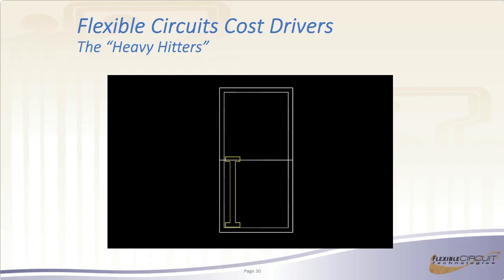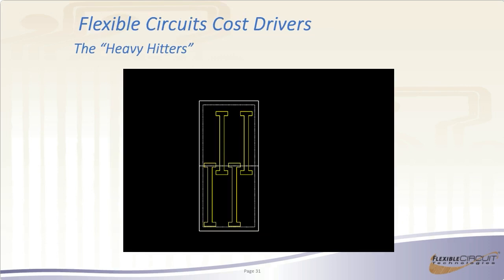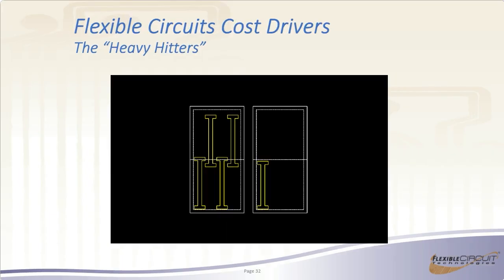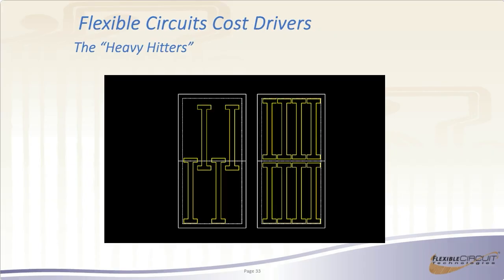No matter how you panelize that, the best you're going to be able to do is get 4 parts on a panel. Now, if it turns out that he put a little extra service loop in there that he didn't need and could get by a little bit less and was able to size it so it's just slightly less than half, he can now get 8 parts on a panel. So that extra 3/8 of an inch doubled the price of the circuit. So it can have a huge impact.